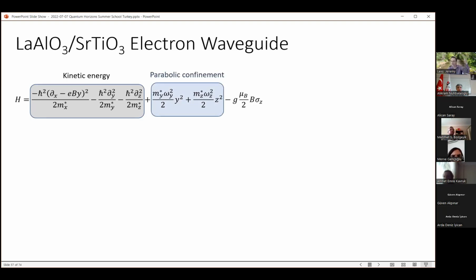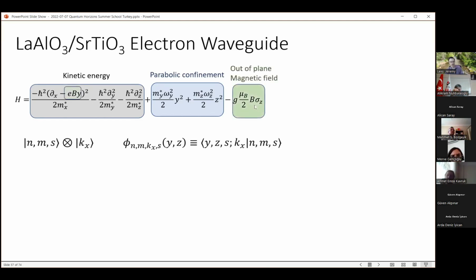You get evenly spaced energy states. The only difference between the y direction, which is lateral, and the z direction, which is vertical, is that in the vertical direction, it's a half parabola. So it's basically a parabola that goes to infinity at the interface. But we know how to solve that. You just remove all the even states, and it's a trick that everybody does. And then you have magnetic field that couples to the vector potential and then to the spin. If you solve this, you get energies, eigenvalues, and eigenstates.